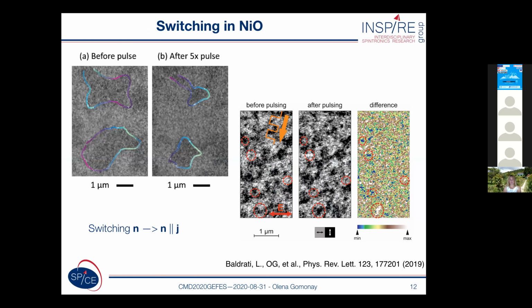So we really observe a switching in the direction parallel to the current, as can be deduced from the XMLD data. You see the circles which demonstrate switching from black to white domains in the right part of the slide, and also in the color figure you see the domains which switch, the regions which switch. Of course, when we worked on this data, we have seen that some of the regions were switched in the opposite direction, but we attributed this to the dissipative forces which inevitably were present in this sample.